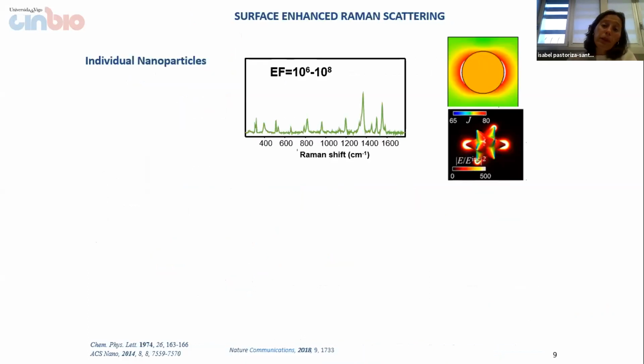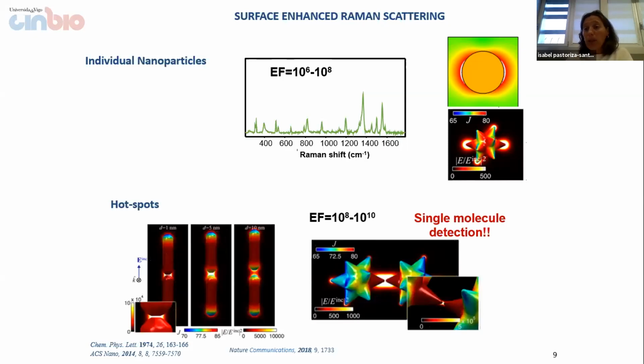So we know that an individual metal nanoparticle can enhance the Raman signal of a molecule by 10 to the 6 to 10 to the 8, but this enhancement can be even higher in the case of having self-assembly of nanoparticles, and this is because of the formation of what are called hot spots. This means huge electromagnetic fields that are generated at the gaps between the nanoparticles. Imagine if we are able to locate the molecule in the gap, we would be able to enhance the Raman signal. In the case of having hot spots, the enhancement factor can be even 2 orders of magnitude larger than in the case of an individual nanoparticle.